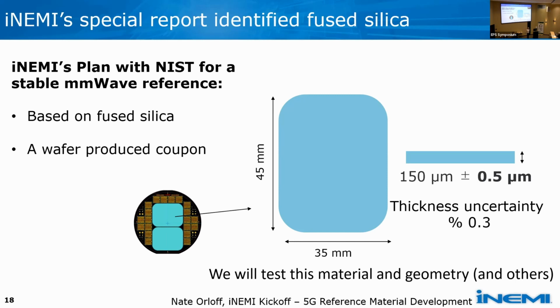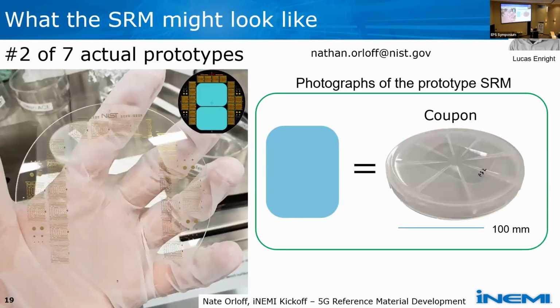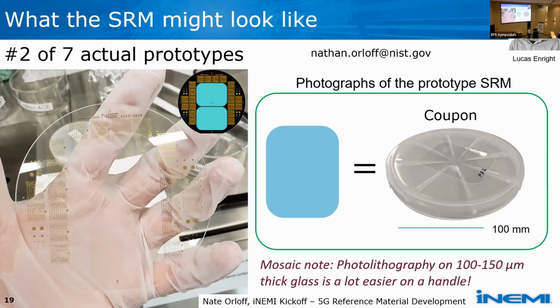The difficulty is that the requirements on TTV for this are very tight. You want a thin material, sort of 150 microns or 100 micron thick, and you want very tight TTV so that the thickness uncertainty is reduced. And if you do want to fabricate some of those structures around the edges, I have to say, you're going to find that a lot easier if you have a handle wafer. In fact, what is pictured here is a reference sample that was made earlier with a handle. So it gives you the ability to handle that without a lot of problems.